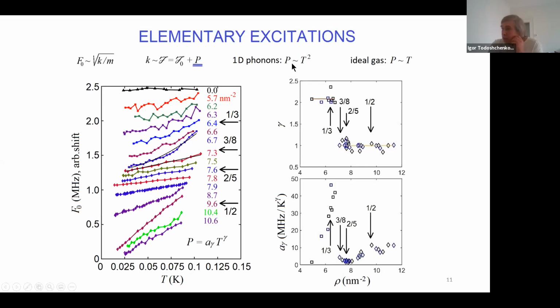We know from one-dimensional formulas that the pressure of the system is proportional to T squared. In 3D, energy is proportional to T to the fourth, and pressure is also proportional to T to the fourth. In the case of 1D, it's T squared. And that's what we see at densities not very high, corresponding to the 1/3 normal phase. These indeed look like a square dependence on temperature. But when we enter the dimer phases, abruptly this quadratic behavior changes to linear.